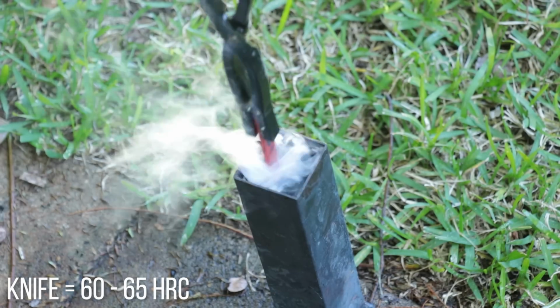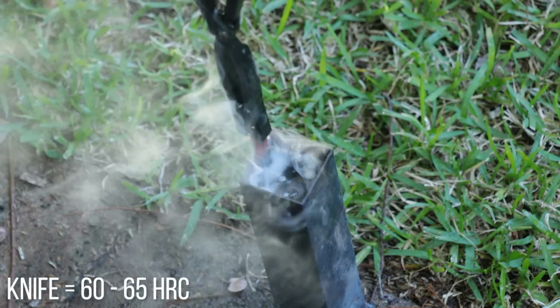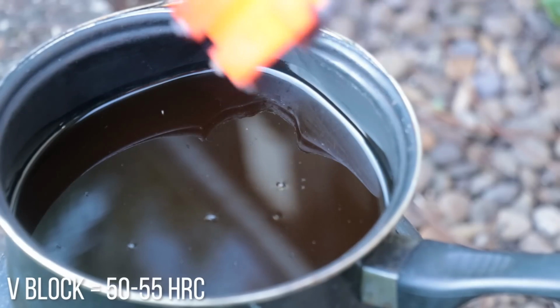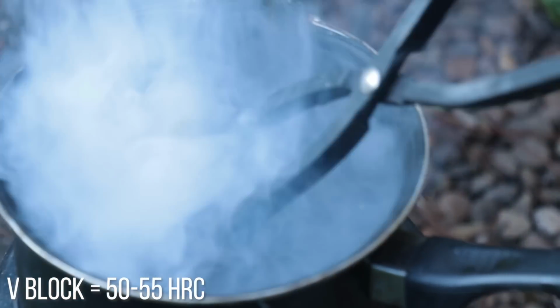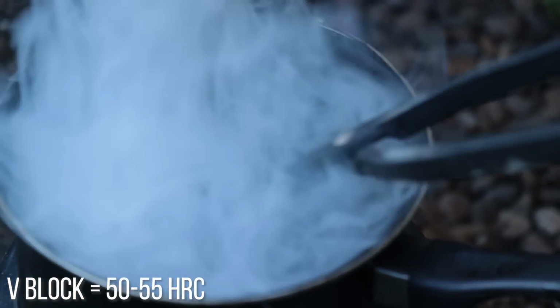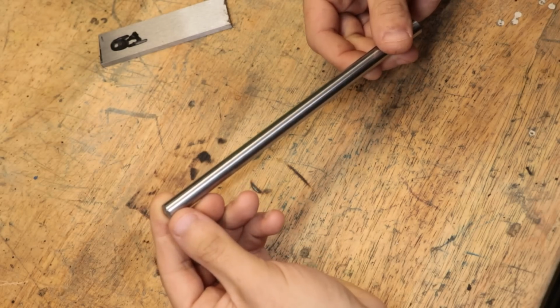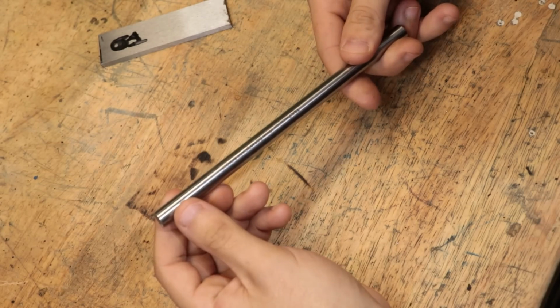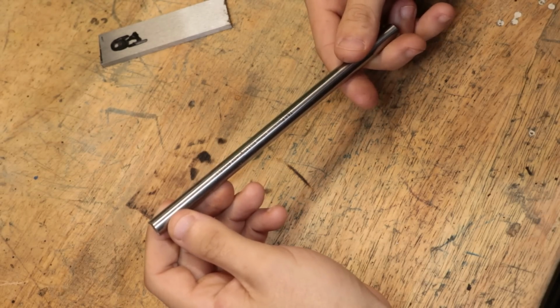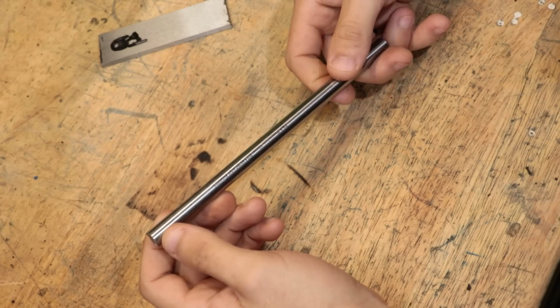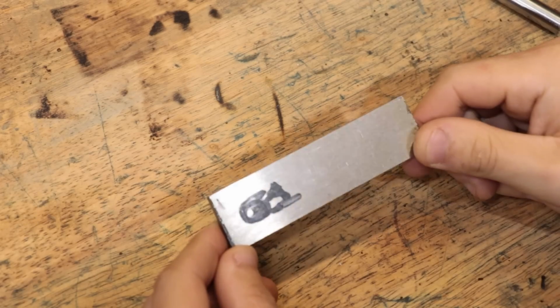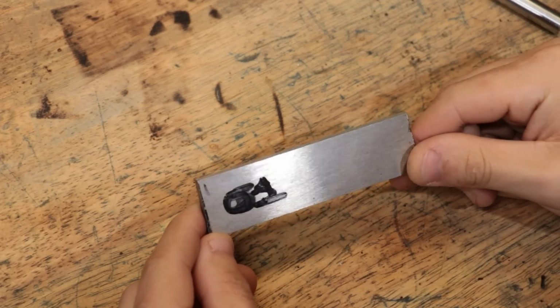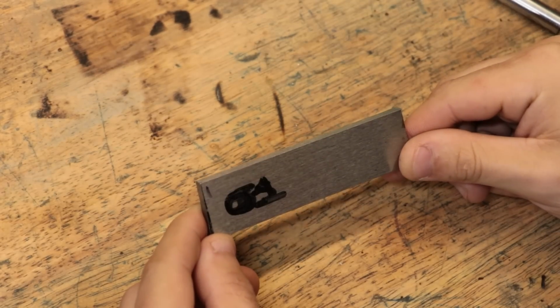With small parts, I can generally get close to 65 Rockwell C hardness, but as the part grows, the hardness does tend to drop into the mid-50s. Now, if I'm not looking to get the maximum hardness, then that probably won't be an issue, because I can simply temper it back to what I need and go from there. But if it isn't hard enough, I can then switch over to using our O1 or oil hardening steel.